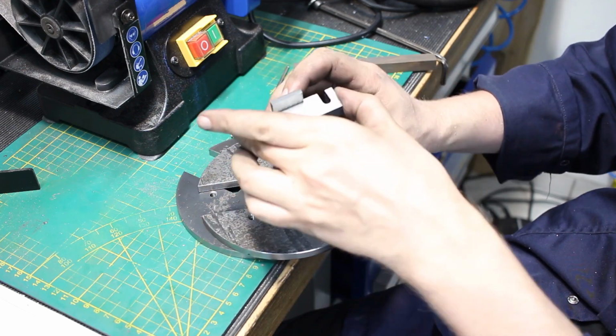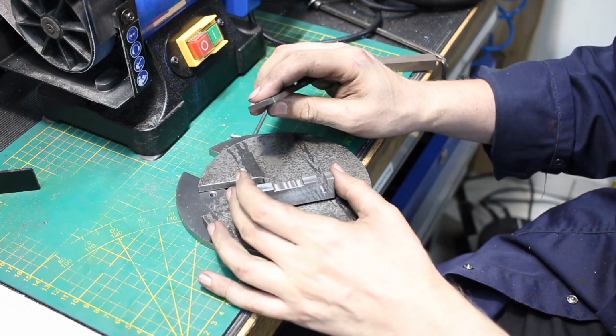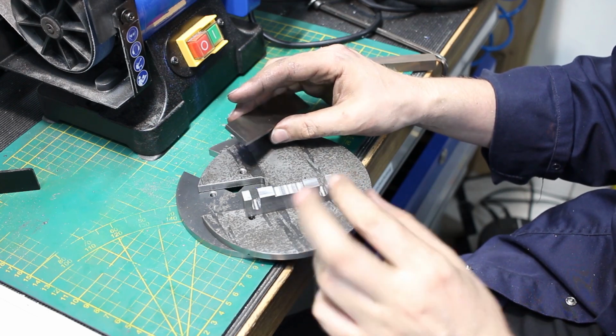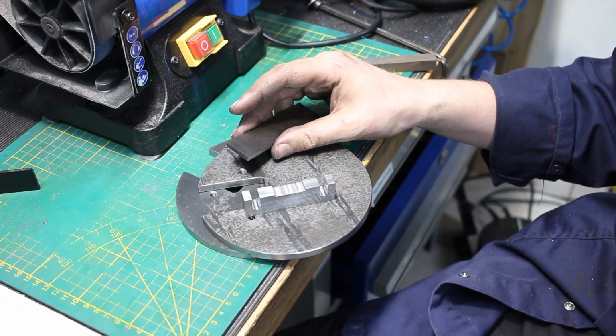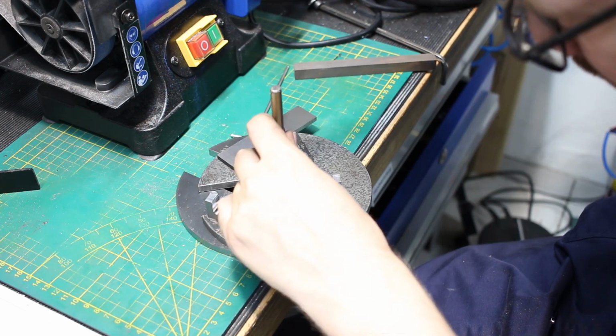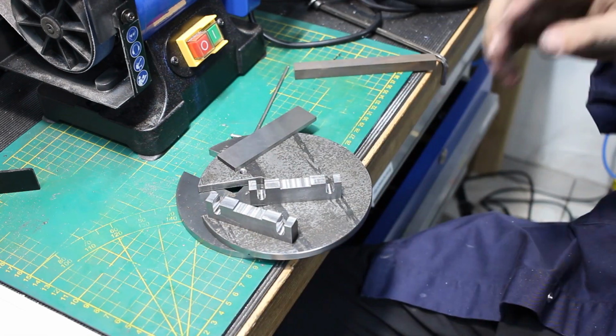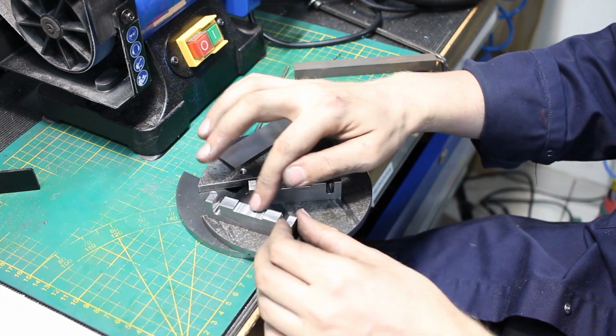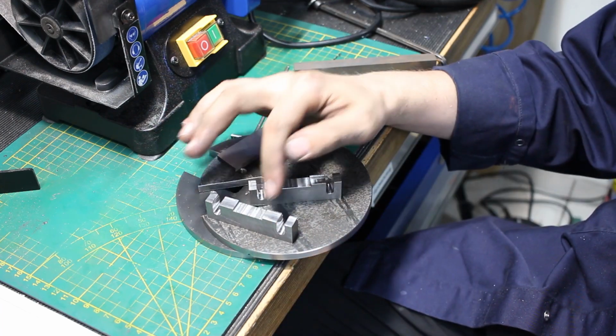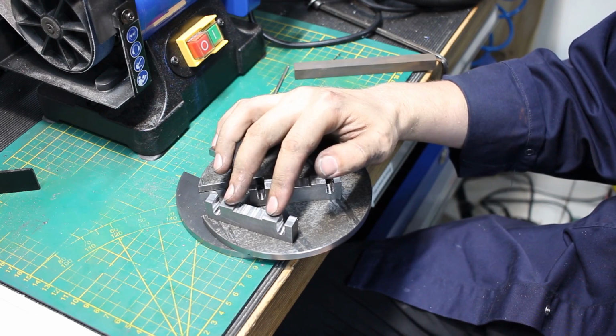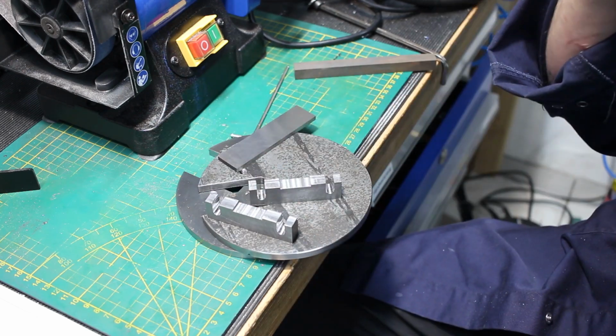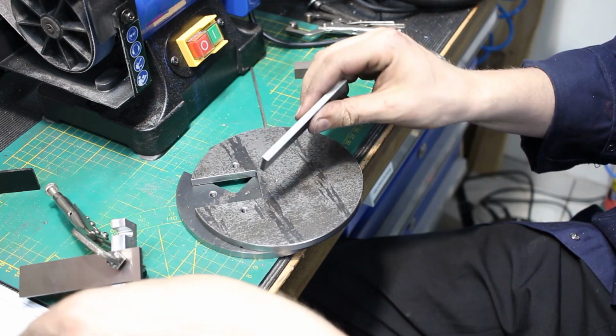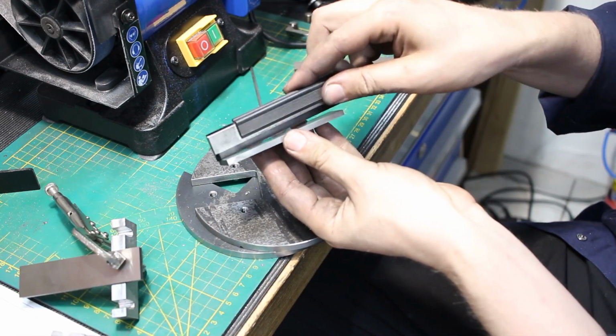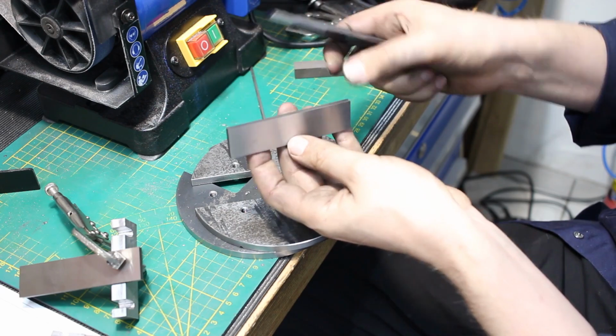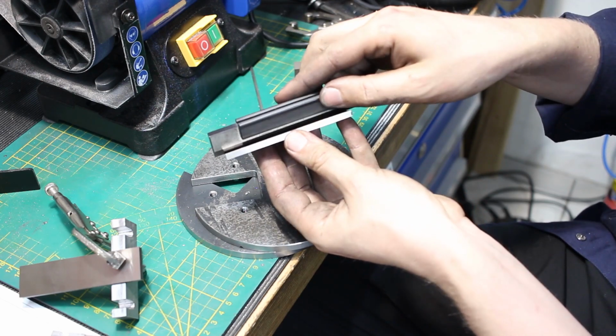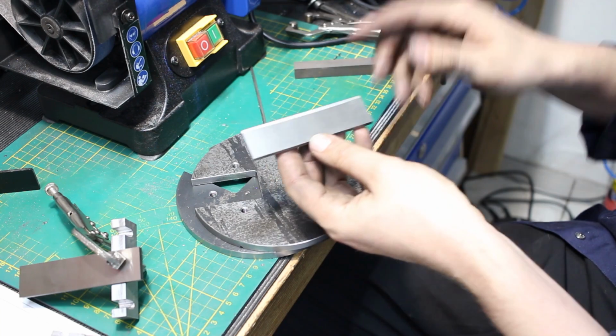This gives you about 0.05 to 0.1 millimeters of gap. That's where your silver solder can flow. Same on this one. There we go. Now we can clamp it shut, but we still have a gap for the solder to go. Of course, we have to put the flux between those two parts before we clamp it together. One thing I was surprised, the high-speed steel blank did basically not move when I removed almost 1 millimeter of material from one side. It's still straight as an arrow.